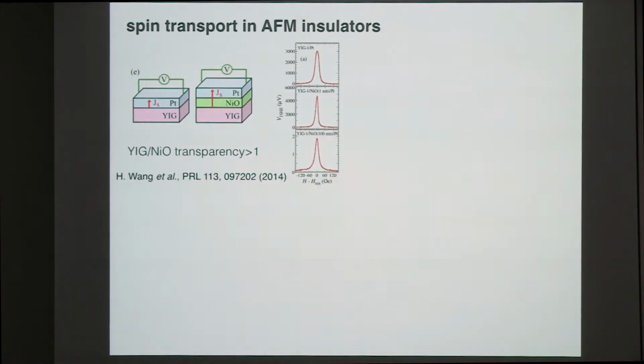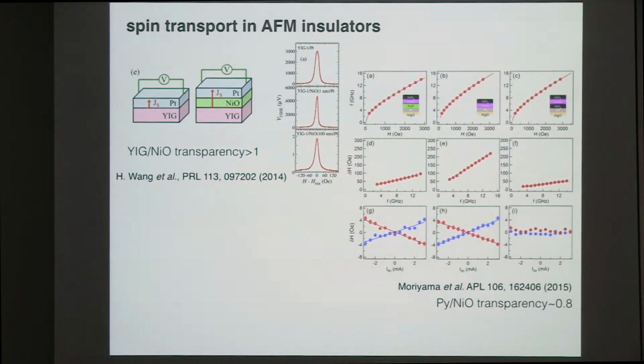And for the insulators, there is also progress. This pioneering work is from Ohio State University, and they show they can do spin pumping in the platinum bilayer, and they compare this signal with the signal from the trilayer system with a nickel oxide interlayer. They even find that the spin pumping can be further enhanced even with this additional layer of antiferromagnet. Another very important work from Moriyama-san shows that even when you grow this material to 10 nanometers, the transparency is still 0.8, which means this material is very good for spin current transmission.